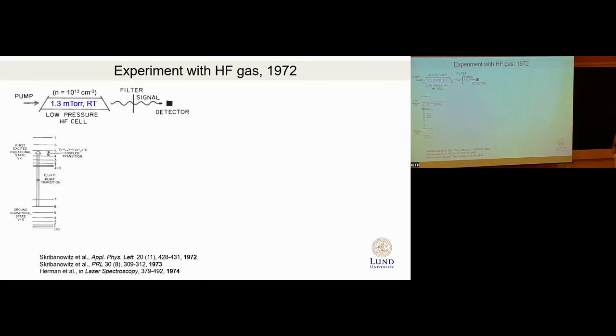It was done with hydrogen fluoride gas at room temperature at MIT, in the Feld group. They used this cylindrical cell with a low pressure of hydrogen fluoride, 1.3 millitorr, or 10 to the 13 per cubic centimeter. So basically it's 10 molecules per every cubic micrometer. So the collisional times are very long, meaning that once you excite the molecule, the coherence of this excitation persists for a very long time.